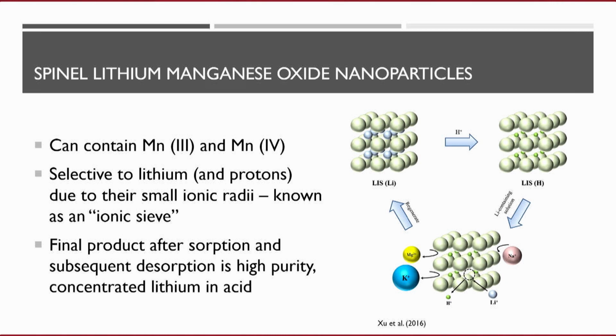There are many types that are used, but the most popular ones being used in this industry, and I would argue being researched in academia, are manganese oxide. They're called spinel lithium manganese oxide. In this case, nanoparticles. These are synthetic minerals that we're making in the lab. Starting in the upper left of the diagram on the right-hand side, what you do is you take the ingredients of this mineral that you want to synthesize, put them in the presence of lithium, and you calcine that mineral. And because lithium is present, you can see the blue spheres in there. Those are lithium ions that are inside of the mineral structure in what are called ion exchange sites. So when you synthesize it, you make vacancies in there that are exactly the size of a lithium ion.